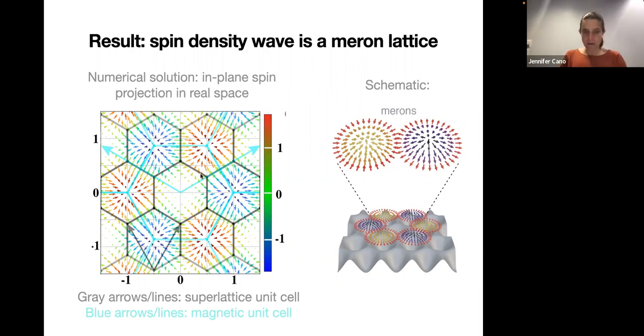So each hexagon is a unit cell of our potential. So remember, we applied this spatially modulated potential. It has a periodicity, and these hexagons tell you that's the unit cell of that periodic pattern. The magnetic order forms a larger supercell where 1 out of every 3 cells is a meron of one orientation, 1 is a meron of the other orientation, and 1 is kind of empty. So this is a rather unusual pattern.